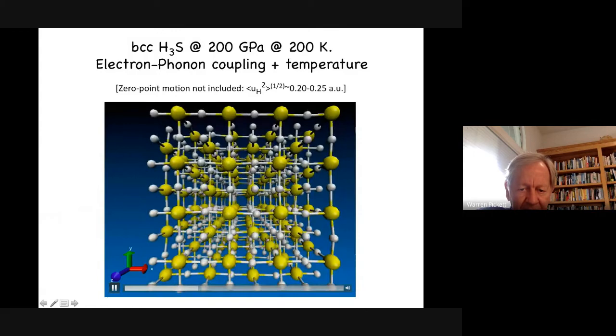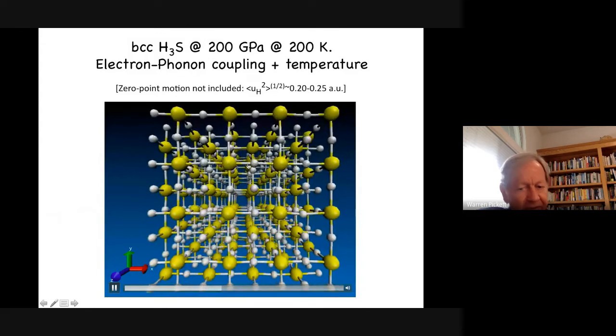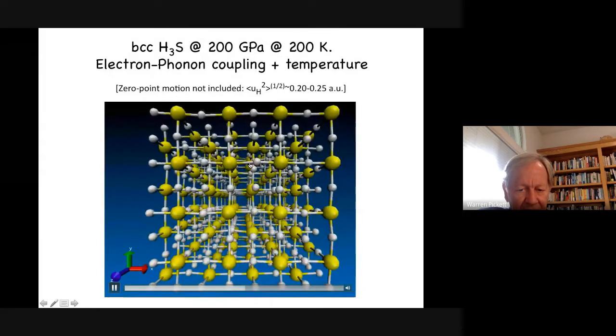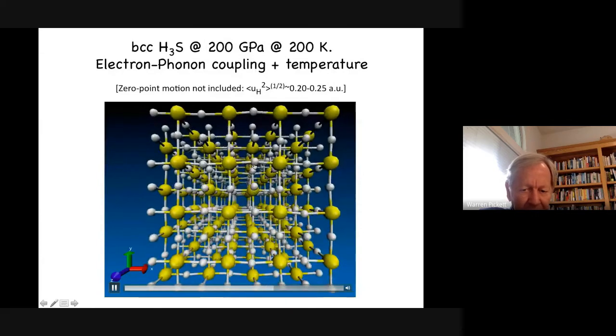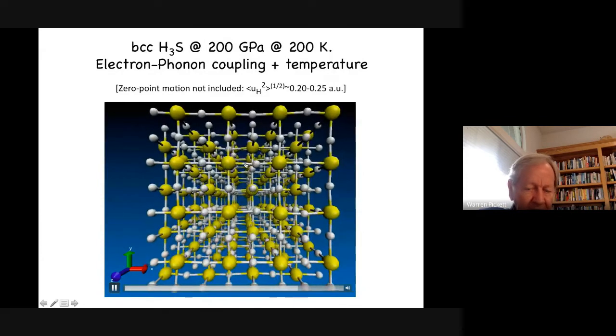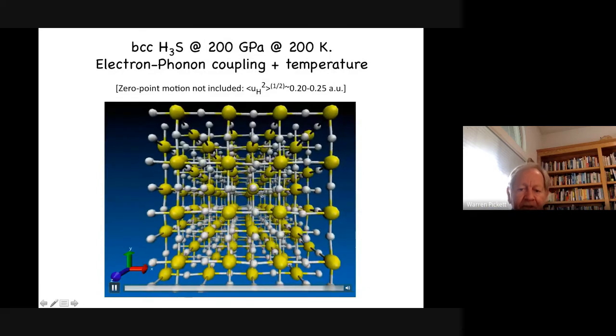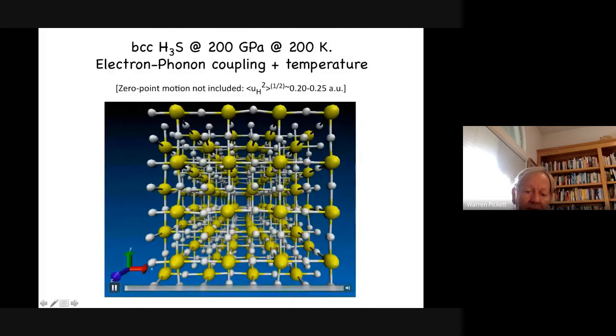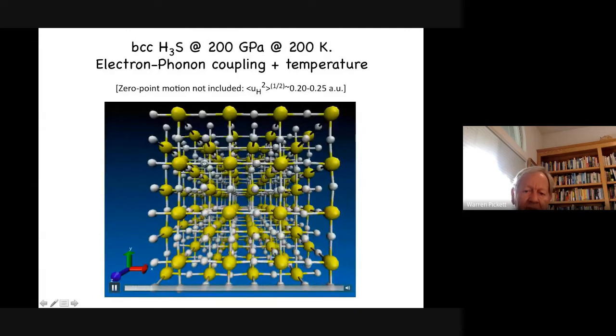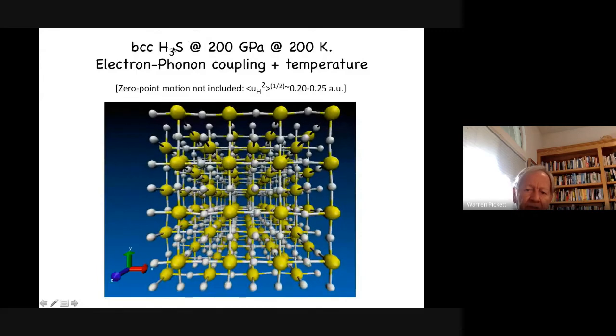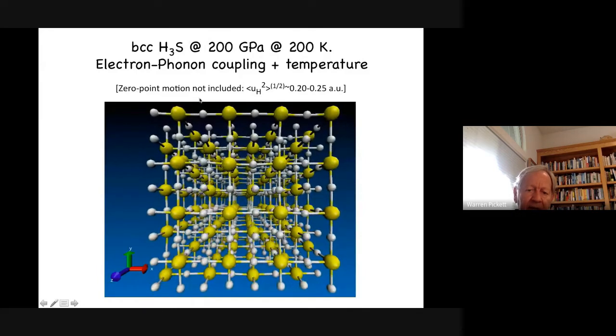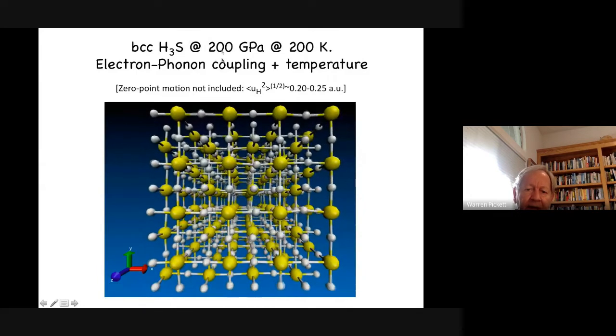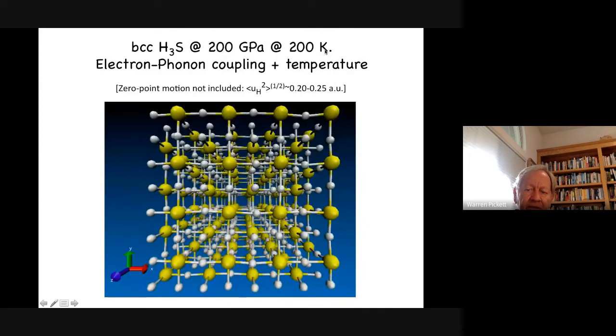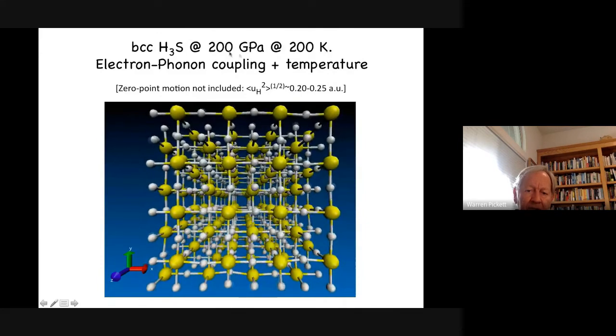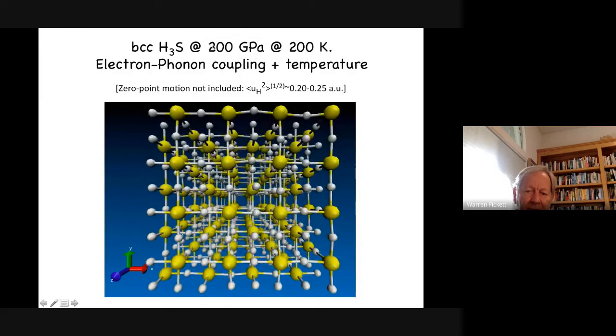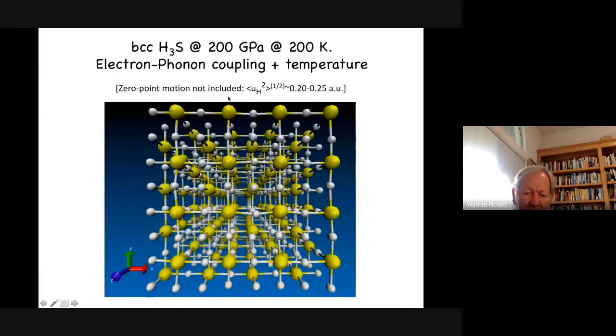So at each little displacement of the atom, you do the calculation again and get the new force, and then move the atoms according to the force a little bit and do the calculation again. What you're seeing here is real hydrogen 3 sulfide vibrating at 200 Kelvin and at pressure corresponding to the maximum TC of this material.